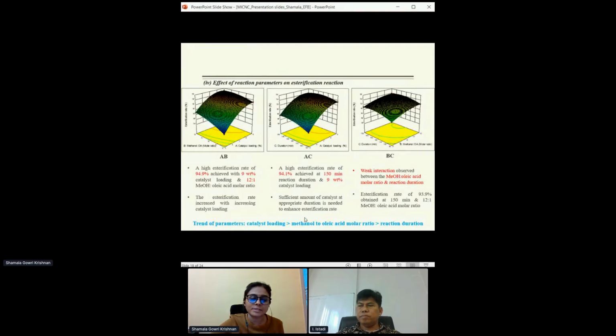However, a weak interaction was observed between the methanol to oleic acid molar ratio and the reaction duration. But the esterification rate was also high at 93.9% at 2.5 hours of reaction for 12 to 1 methanol to oleic acid molar ratio. With this, based on the optimization study, we can say that catalyst loading is the most influential parameter in the esterification reaction, followed by methanol to oleic acid molar ratio and reaction duration.